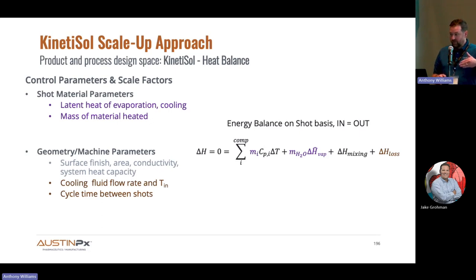because after we made our first scale change, the next thing we want to do is switch to a continuous mode. And usually the objective there is to deliver volume, throughput, maximize yields. And so as we start to speed the process up, the starting temperature of the system, this T1, might be different. But again, we know we need to put a certain amount of energy into the mixture to dissolve the drug in the polymer, but we don't want to put too much in the wrong way because that could cause degradation. So there's a balance here.